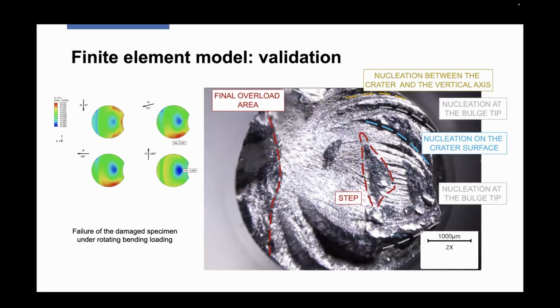Okay, so we validated this finite element model for one impact case, an impact velocity of 100 meters per second. And here you can see what happens after the impact if we load the specimen with a rotating bending moment. So you can see different bending moment positions.